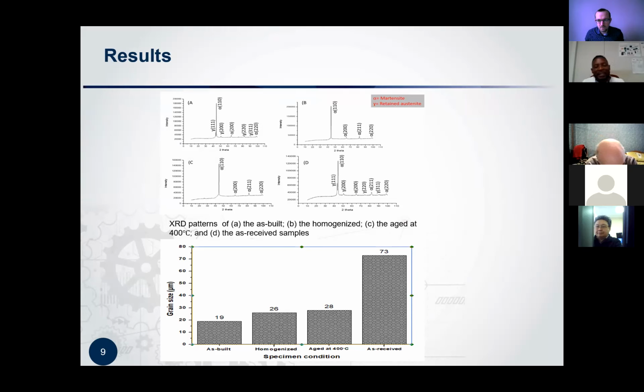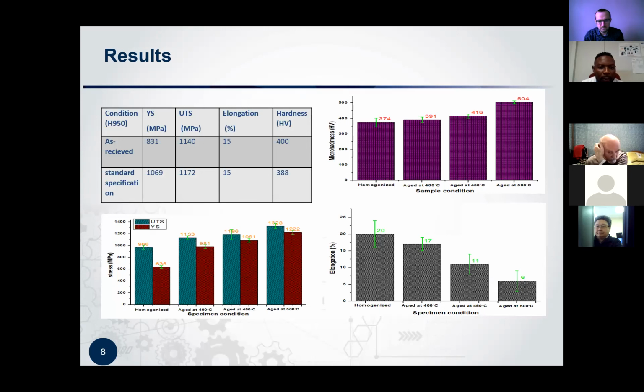No, we didn't measure that. It was due to budget, because I had to just focus on the one which gave us the conditions we're looking for. So I didn't measure that one. Okay, and have you got any correlation between the hardness and the grain size? Yeah, there is. You can see for the as received, it was 400, and for the aged condition, it was higher. So there is a correlation. There is a trend between those two. Mm-hmm. Yeah. I can't see the grain size here, but no.